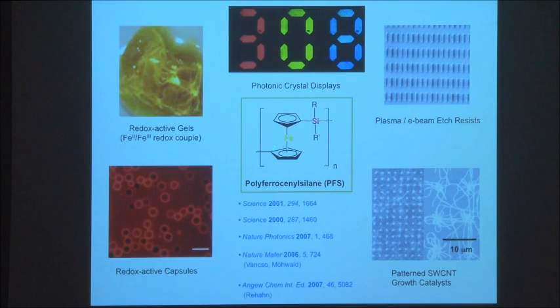You can make gels, which as you oxidize and reduce them, will swell and contract. And this has been used actually as a basis for photonic crystal display. So this display here is not an LED display. It's actually a photonic crystal display. It's made from a thin film of one of these gels on indium tin oxide, where the thin film is filled with silica microspheres. And when you oxidize the gel, it will expand and the spacing between the microspheres will change. And so the light that's scattered by Bragg scattering will change wavelength. And you can use this actually to make displays as shown here. And if you're interested in this, there's some papers down here which describe this.